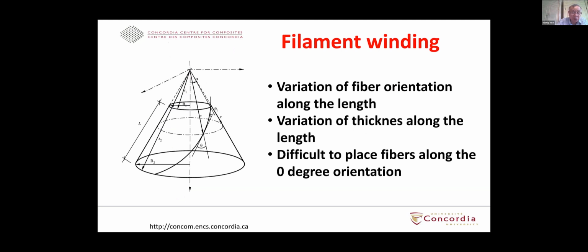One of the techniques people use to make the composite cone is filament winding. You can see you first need to have a mandrel, and then you wind fibers on top of that. This is the meridian, and it depends on the angle that you want to wind. But because you have a smaller diameter at one end and a larger diameter at the other end, in filament winding you end up not having the same fiber angle. The fiber angle is defined as the angle between the direction of the fiber and the meridian. So here, for example, you have θ1 at this location, and you have θ at another location. The issue with this filament winding method is that you have a variation of fiber orientation along the length.